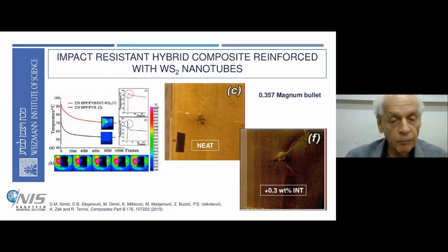You see that the temperature in the neat case went down very fast, because there was almost no friction between the bullet and the aramid fabric. While when the nanotubes were in, the temperature did not go down very fast, because there was a lot of friction, a lot of interaction between the bullet and the fabric, and consequently the temperature went down much slower.